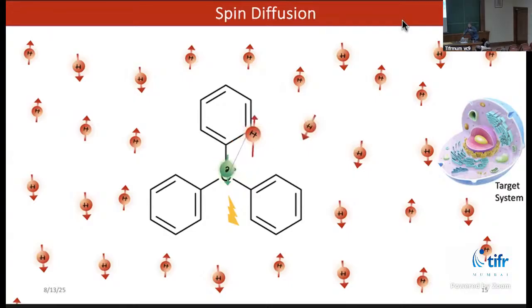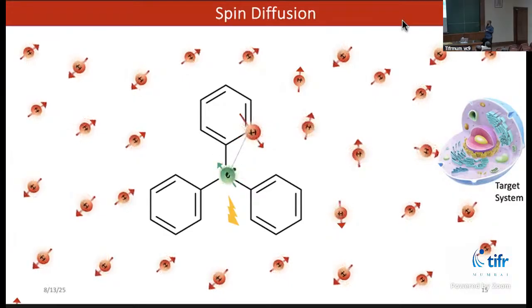And this flip-flop process will continue to the bulk. So once we induce the flip-flop between electron and nucleus, and if the two nuclei are coupled, the two nuclei can flip-flop. And this process can happen in the bulk. So eventually, after a certain time of irradiation, one would see there is flip-flop process and the polarization will diffuse to the bulk.